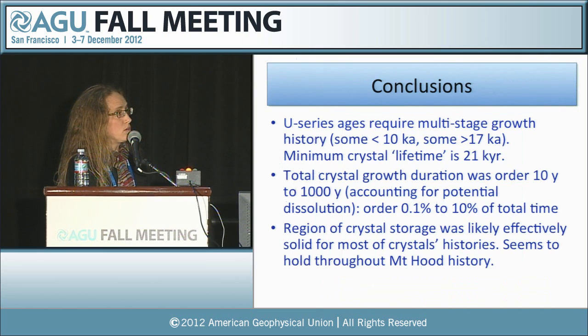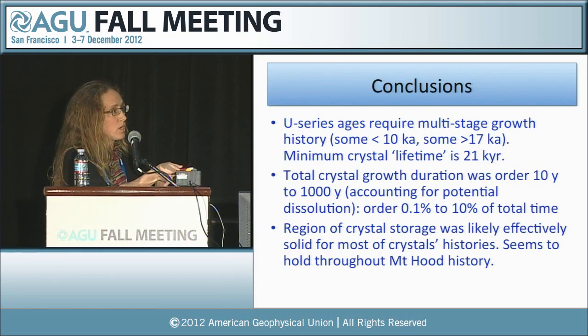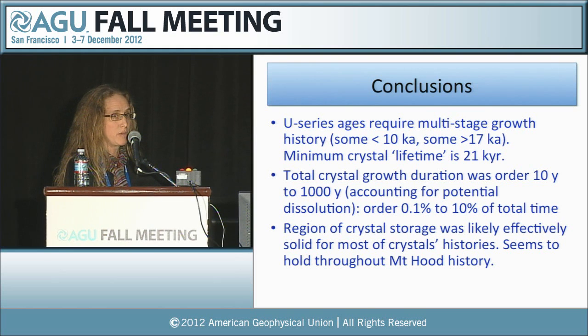Okay, so in conclusion, we can use the U-series ages to constrain a minimum total time, and again this could be much longer than this, but within that we can also say something about the total growth duration on the order of tens of years to maybe 1,000 years, even accounting for potential dissolution. That's still on the order of a fraction of a percent up to about 10% of the total time. And what this implies is that the region of crystal storage was very likely to be effectively solid for most of the history of these particular crystals.